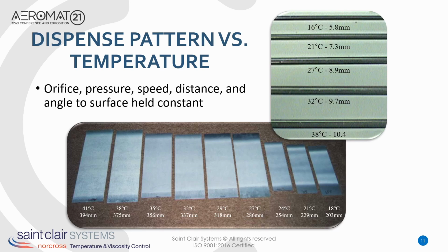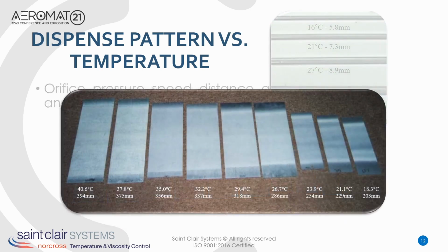Let's start by examining a standard spray system. In this anti-chip sealer application, we can see the impact of temperature on dispense and ultimately on performance. The most obvious change is in the width of the fan pattern, but perhaps even more important is the impact of viscosity on spray consistency. Above 35 degrees C, the coating is thin and uneven. You can see the substrate peeking through. Even if it adheres well, it can't do its job.